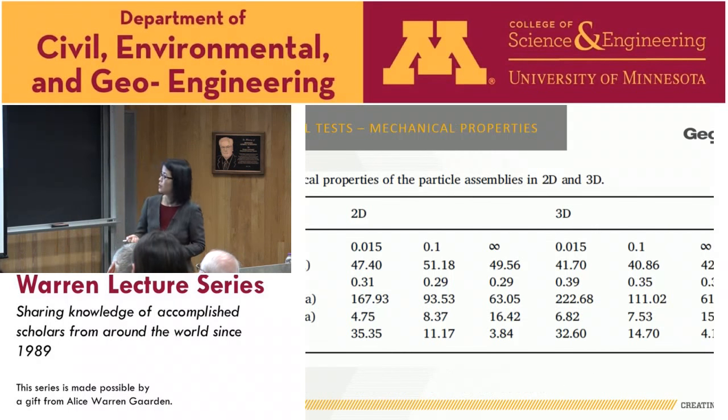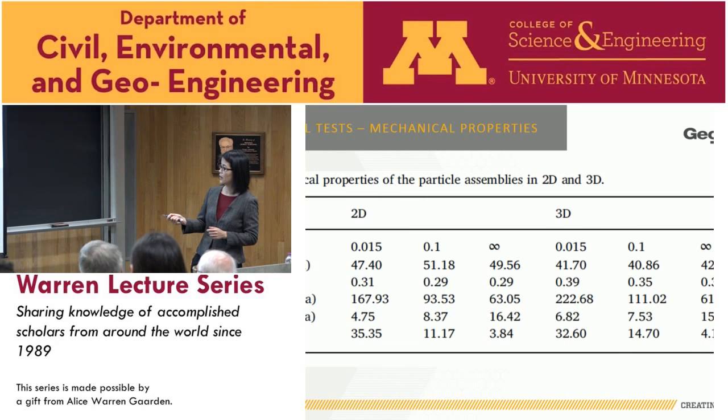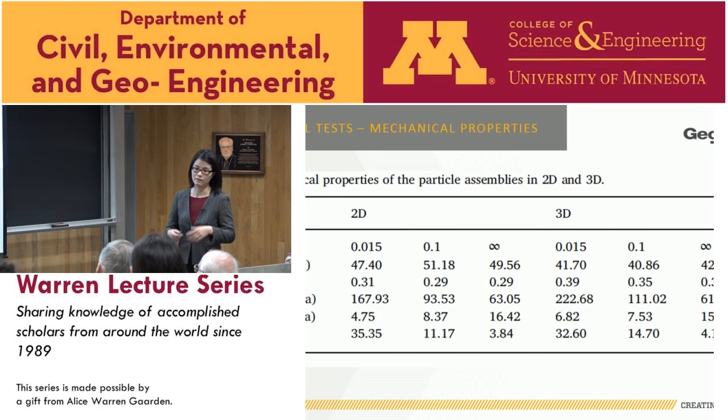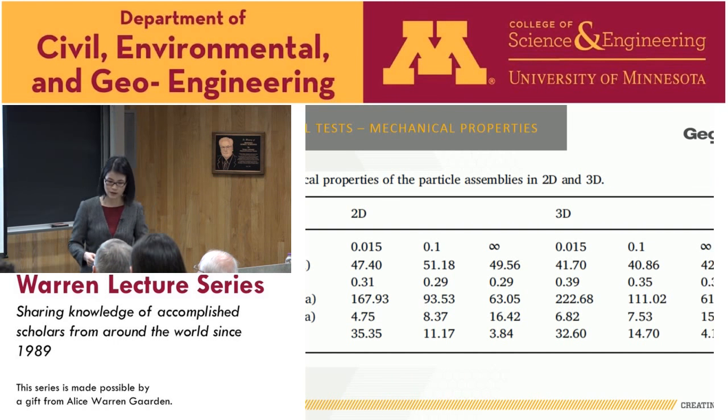Now that's a summary of the strength we get and the strength ratio. If we look at the strength ratio, the infinite case, the elasto-perfect brittle, is still about 4 in 3D. But for the very small beta, significant softening, we get a strength ratio over 30. That's very, very high. And again, in the beginning, I was very surprised.